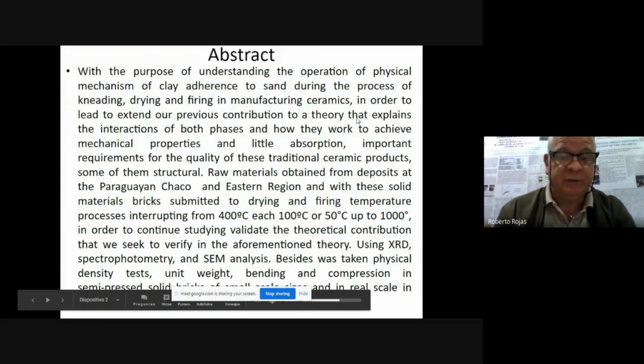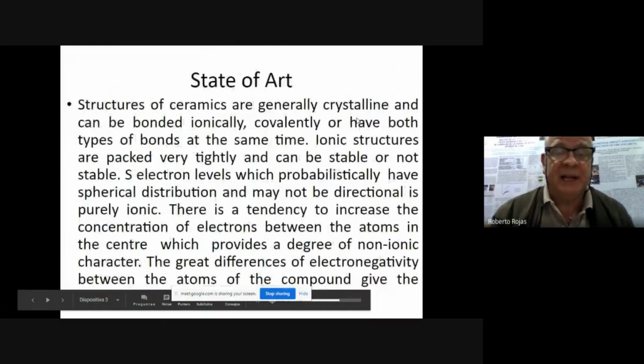We find ceramics with material from Paraguay, the Chaco and the eastern region in Paraguay. We have tested and made some samples at different temperatures in the oven, up to nearly 1,000 degrees centigrade, every 100 degrees. We also use SEM analysis to verify that the theory is okay. Yes, we try to find that in this research.